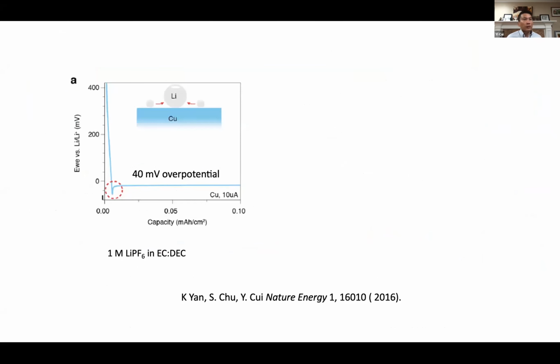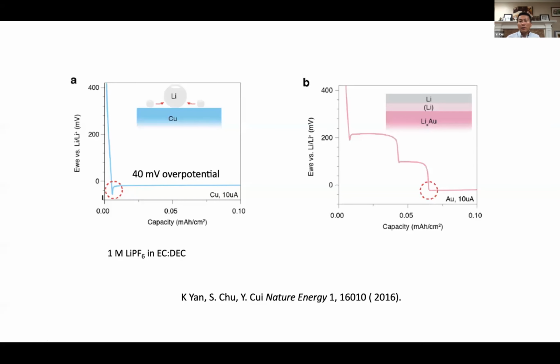One key finding to really underline the concept of host is a controlled deposition of lithium to the location you want. So in 2016, in this Nature Energy paper, we show, for example, on copper, if you plate lithium, there's a nucleation barrier in the voltage curve and then plating takes place, 40 millivolt under 10 microamp, very low current density, 10 microamp per centimeter square. And gold has no nucleation barrier. Certainly there are two categories of material. Some have a nucleation barrier, others don't. And what's the reason behind this?